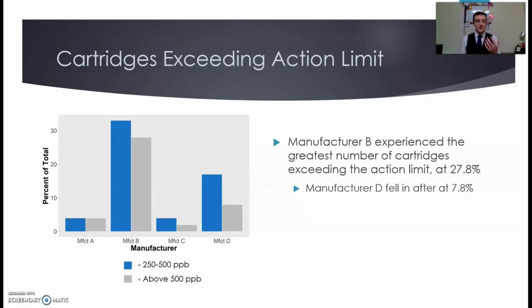This plot summarizes the concentration data from the past two slides as percentages falling within certain concentration ranges, with the blue bar representing concentrations between 250 and 500 parts per billion, and the gray bar representing concentrations above that action limit of 500 parts per billion.